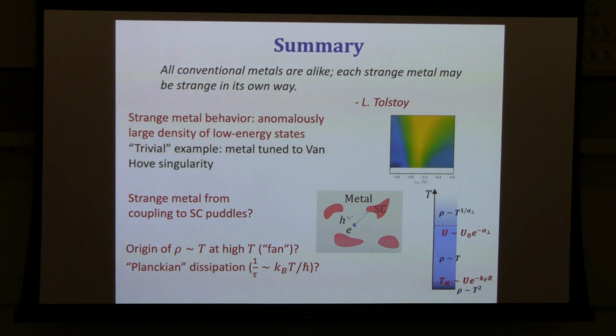We say nothing here about so-called Planckian dissipation in many of these systems where the resistivity is linear in temperature. It looks like the scattering rate actually scales with temperature in this very simple form with a coefficient which is of order one. We have nothing to say about that. We actually mostly approach the problem from the regime where this coefficient is much smaller than 1, and we have to extrapolate to get 1. Okay, so with that, let me conclude. Thank you very much.